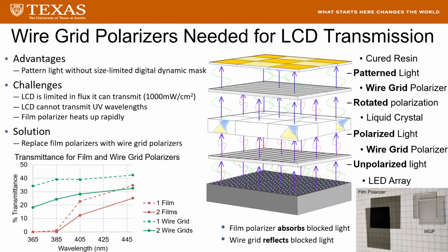You can see some transmittance data for film and wire grid polarizers in the bottom left-hand corner. And you can see that wire grid polarizers transmit light at every wavelength in the UV, near UV region much more efficiently than film polarizers, even down to 365 nanometers. In addition, since wire grid polarizers are reflective polarizers rather than absorptive polarizers, they don't heat up as rapidly under illumination, allowing you to illuminate the LCD at much higher intensities without overheating the screen.